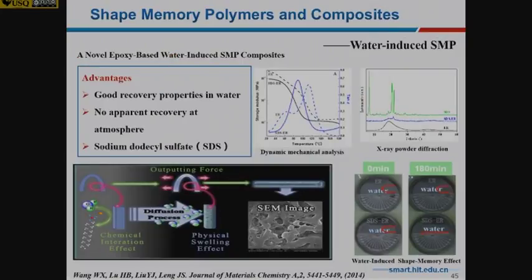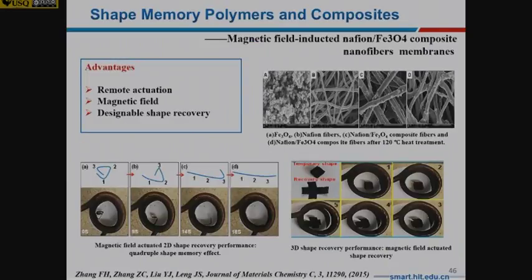And for the thermosetting polymer, we do find epoxy can also be driven by water. You can see from the right-hand side, if you put the water, which is red color, in the polymer, this can deploy within 180 minutes. This is because on the polymer surface, we can have some SDS to make some holes to allow the polymer to have more absorption of the water. So this is another idea, using magnetic field.